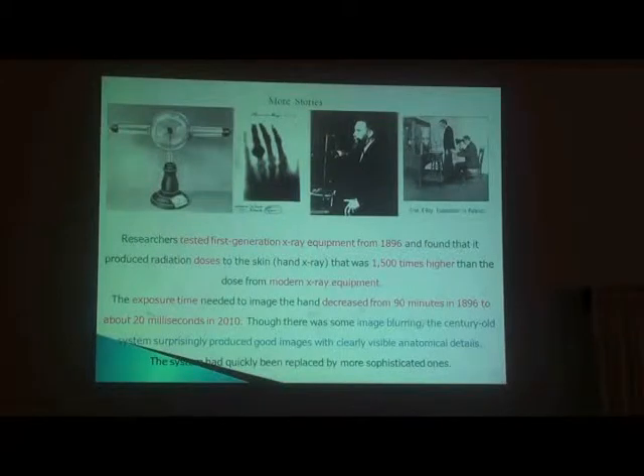And now we know how dangerous it is. But immediately after the invention of X-ray, the hazardous effects of X-rays were not known. That was the fact. If you look at this, the skin dose was 1500 times higher than the dose of modern X-ray equipment. Right now, whatever X-ray equipment we have, the intensity of the beam that came out from the early equipment was 1500 times higher. Exposure time is decreased from 90 minutes to about 20 milliseconds.